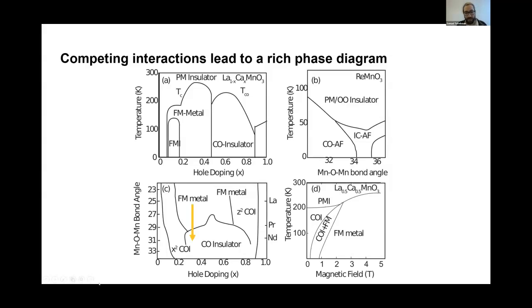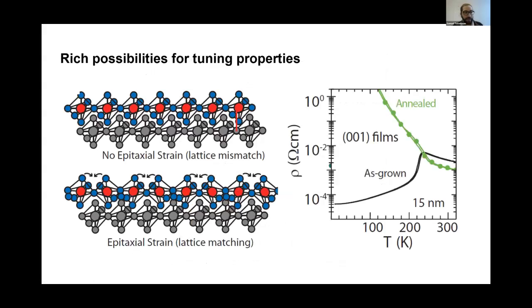What I'm going to talk about today is essentially trying to go from a ferromagnetic metal into the charge ordered insulator phase at constant hole doping by changing this manganese oxygen manganese bond angle by applying a strain. The system we're going to study today is an epitaxial thin film of LCMO. So this is 1/3 doped LCMO. In bulk, it's a ferromagnetic metal. However, when you deposit it on a thin film that has a different lattice constant, the epitaxial strain that you get from the thin film is going to change that manganese oxygen manganese bond angle, which is going to change the hopping interaction, which is going to favor the insulating state.